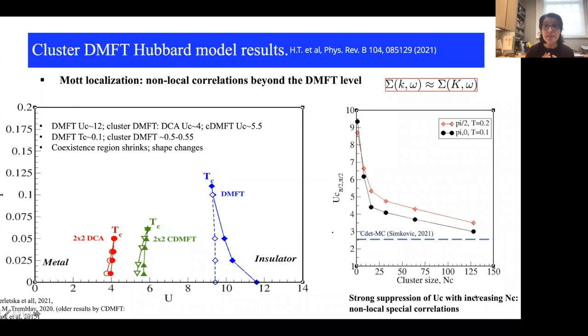Okay, so recently we have applied this method to look at how non-local spatial fluctuations affect the metal-insulator transition in the Hubbard model. So these are the results for the temperature-U phase diagram. These are the results I have shown to you for DMFT. And now here in red and green, we have results obtained in our group by DCA, 2 by 2, the smallest cluster DCA. So this is a cluster in momentum space. And here I show data obtained by André-Marie Tremblay for 2 by 2 CDMFT, a real space cluster analysis.